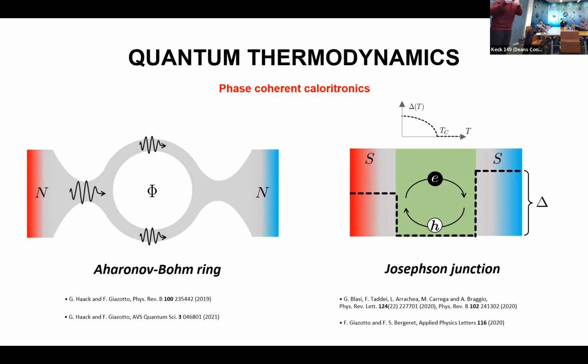And because of this thermal dependence of the gap, whenever you apply a thermal gradient to your system, you break the left-right symmetry of your system. And doing that, you can force heat current to preferentially move in one direction only. And by exploiting this feature, you can realize what is actually the thermal version of the electrical diodes.